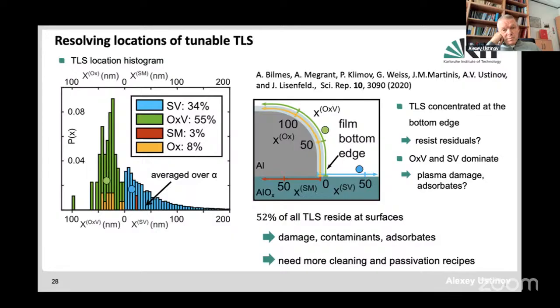We also cannot, of course, tell here whether these are plasma damage during circuit fabrication, or adsorbates. But obviously, the surface needs better cleaning and also needs passivation recipes to avoid the formation of these defects. So this is basically a recommendation which comes out from this study to the technologists, to really work on cleaning the interfaces which are exposed to the environment before measuring the circuit in the dilution cryostat.